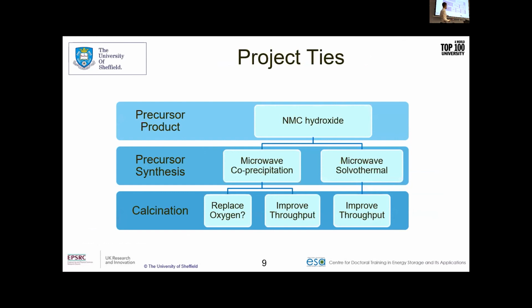So with regards to the calcination step first, we're looking to replace oxygen with a different lithium salt and a different lithium source, that as it heats up, it degrades to form oxygen. So within the crucibles that we put into the furnaces, we've got a localized oxygen. So that's therefore less oxygen stored in the lab, and therefore it's more safe going forward. And also because of that microwave targeted heating, we reduce the calcination time. So say at the moment, this goes at 24 hours, I'm getting it down to 6 hours tops. So we can increase it fourfold.